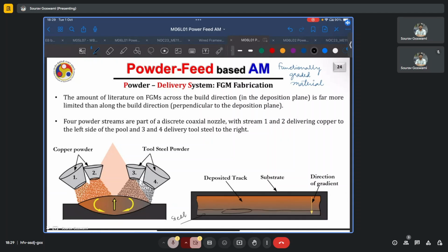And for this section towards the other side, you have this almost orangish section, which is rich in copper. And in between, you'll have some intermediate composition. So even per bead, there is some preferred gradient of composition, which might not always be desirable.